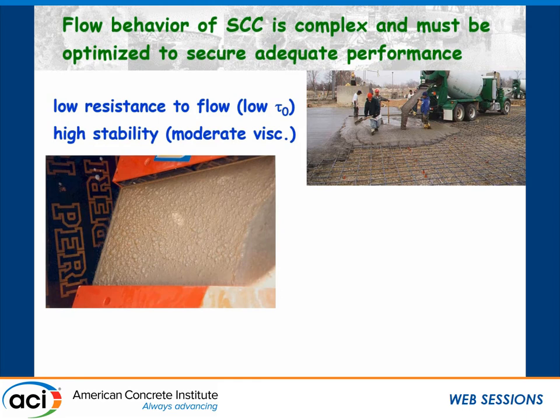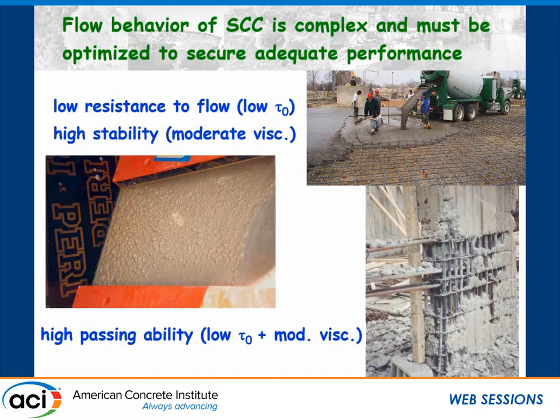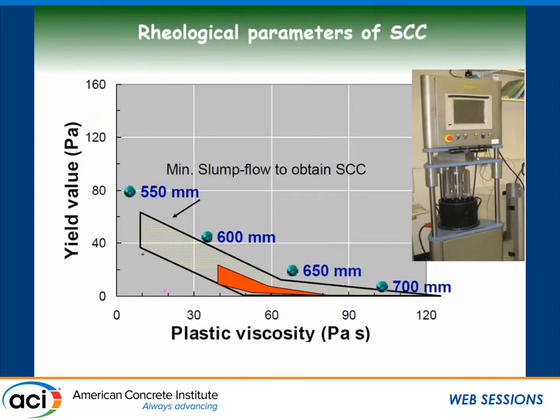Here you have an example of a concrete where the air bubbles are coming to the top, along with some water and paste. This combination of low yield stress and moderate viscosity has to be optimized in order for the concrete to flow under its own weight and ensure complete filling of the formwork without any vibration and without any blockage. So these are the functional requirements, and these are the challenges we have to deal with when proportioning and selecting materials for SCC.